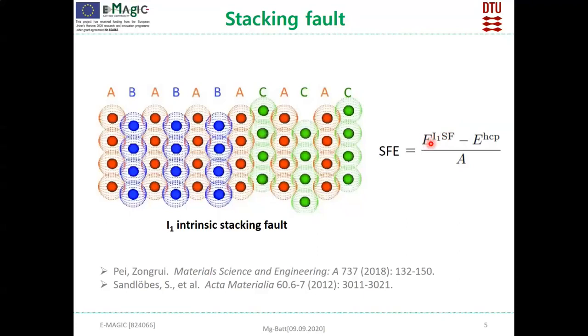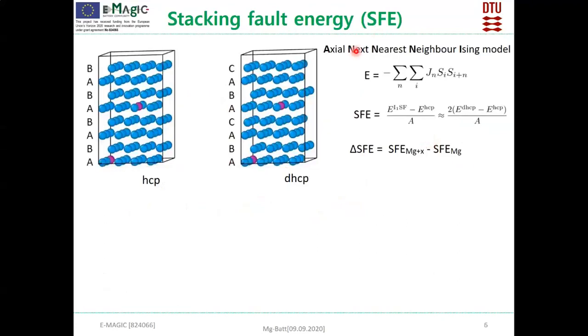And since we are evaluating 33 dopants, in this work we used the axial next nearest neighbor Ising model, in which each stacking sequence is represented with some spin number Si, Si+n, and an interaction parameter is defined between them. Then this results in the stacking fault energy as 2 times E DHCP minus EHCP. So here we can get the stacking fault energy just in terms of two bulk structures: the HCP structure with AB, AB, AB stacking sequence, and a DHCP structure with AB, AC stacking sequence.